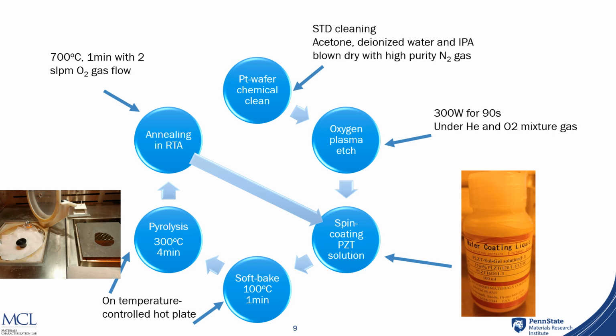So in this method, we're going to take this SiO2 stacked 4-inch wafer. We're going to clean this material, and then we're going to put down our platinum, and after platinum we're going to clean it again before we put down the PZT. So the end goal here is to make sure that if there is a chemical reason for the film failures, we want all the processing to be the same for putting down the PZT layers, as well as, in many cases, we're trying to eliminate impurities.